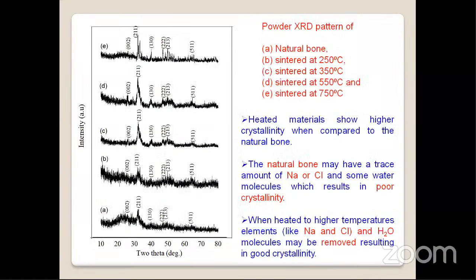Okay, so we have done X-ray diffraction studies over the materials. The first figure, A, is natural bone at room temperature. One could see there are some peaks as well as some noise. Why? The natural hydroxyapatite at room temperature will not show its crystallinity. Because natural hydroxyapatite bone at room temperature has trace amounts of sodium, chlorine, and some water molecules, which result in poor crystallinity.